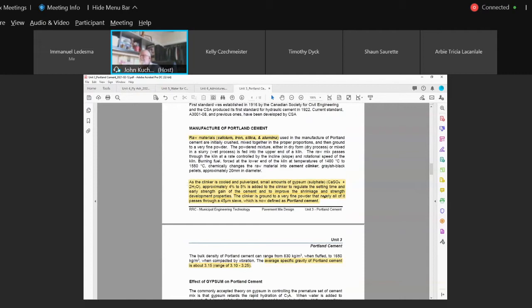Here's the key part now, the last stage essentially where you get Portland cement. When you have a chemical change, you get grayish-black pellets, and these pellets are known as cement clinker. It undergoes another final grinding, which gives you your powdered cement. Chemically it changes the raw material into cement clinker, grayish-black pellets about 20 millimeters in diameter -- not very large, about 3/4 of an inch.